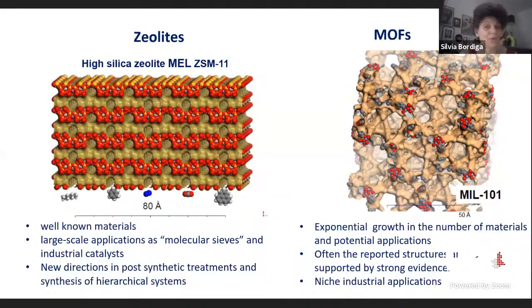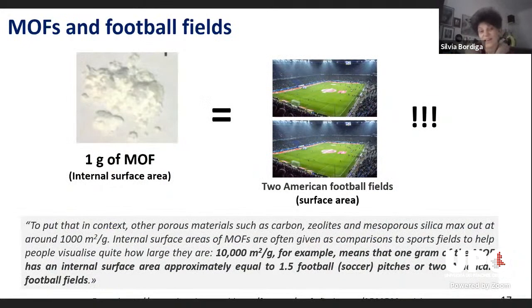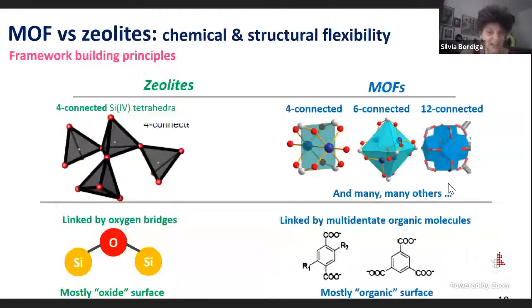In general, however, the major component of these materials is organic, because we have the organic linker, and we have a surface area which is in general an order of magnitude higher with respect to the zeolite class of materials. So in 1 gram of MOF, we have more than one field for soccer, and so it is amazing the space that we have in principle available to run, for instance, reactions.